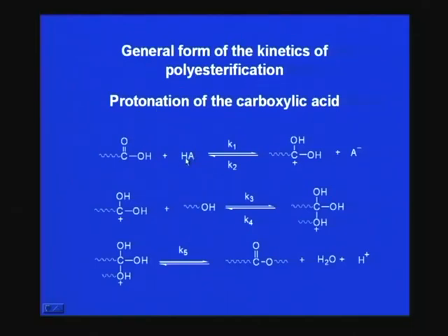So it can add some proton to this thing. So this carbon will be protonated. Now this protonated species will react with the alcohol, forming again this intermediate. This intermediate rearranges itself to form an ester functional group, producing a byproduct molecule, H2O.